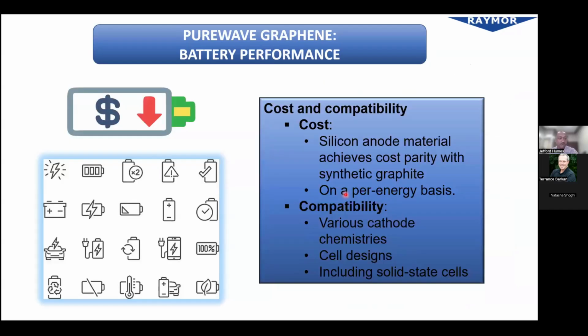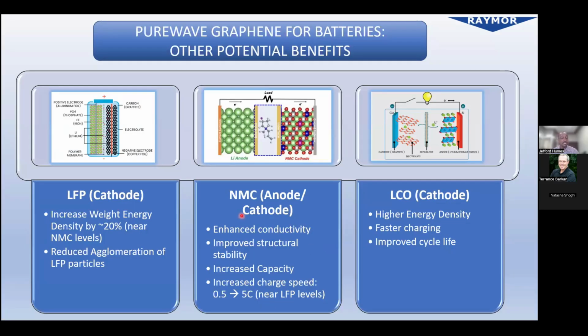Cost and compatibility, of course, is always one of the big concerns. But the silicon anode material that uses our graphene achieves cost parity with synthetic graphite on a per energy basis, and is found to be compatible with various cathode chemistries and cell designs, including solid state cells. Additional battery usages for our graphene can be found within lithium iron phosphate in the cathodes to increase weight energy density and reduce agglomeration of the LFP particles.